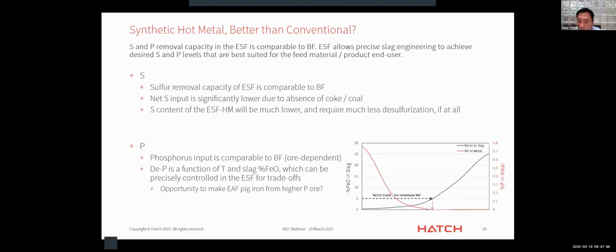Of course, this is subject to the choice of reductants, additives, and reverts you add to the electric smelting furnace, but in general, it will be much lower and require a lot less desulfurization, and perhaps even for some less stringent grades of steel, desulfurization may not even be necessary.